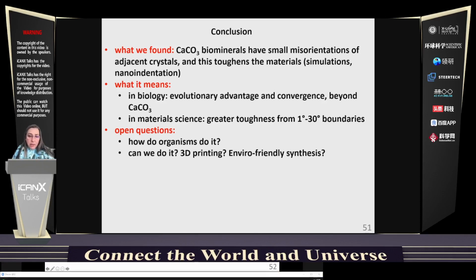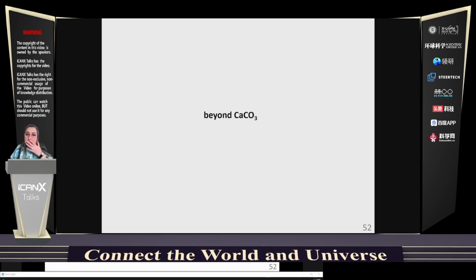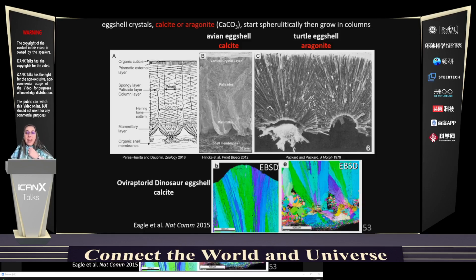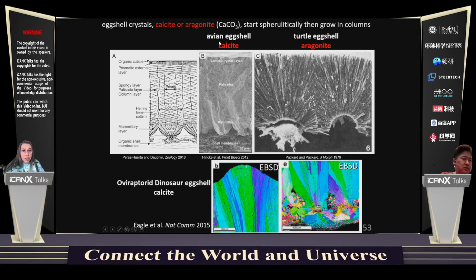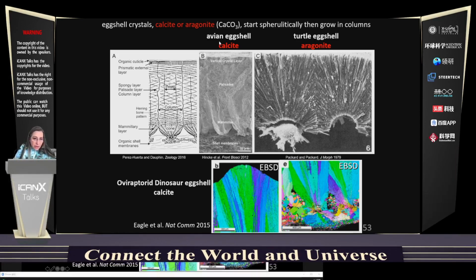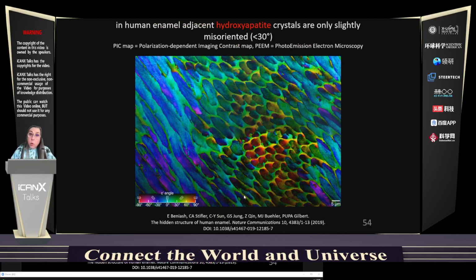I promised to go beyond calcium carbonate, and in the remaining 2 minutes, I'd like to cruise through that and show you that eggshells grow very much spherulitically. They can be made of calcite or aragonite, depending if they are avian eggshells from birds or turtle eggshells. And they start from spherulites, and then they grow columns, and you can see them from the morphology in the scanning electron microscope very clearly. You can see it in EBSD. You can see it in dinosaur eggshells as well. And EBSD shows that adjacent crystals have small misorientations. So this appears to be a bigger, more widely diffused strategy to toughen biominerals.